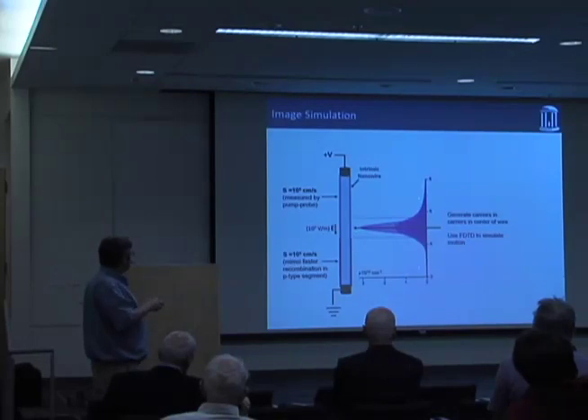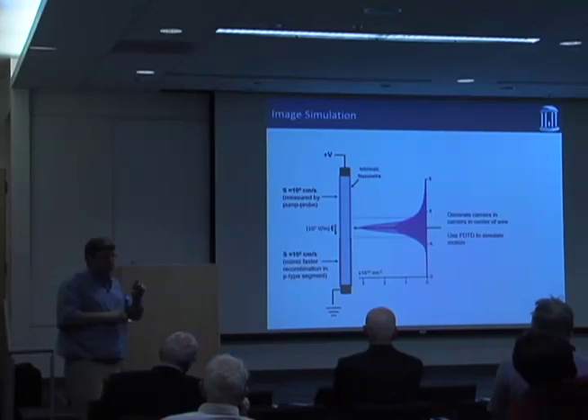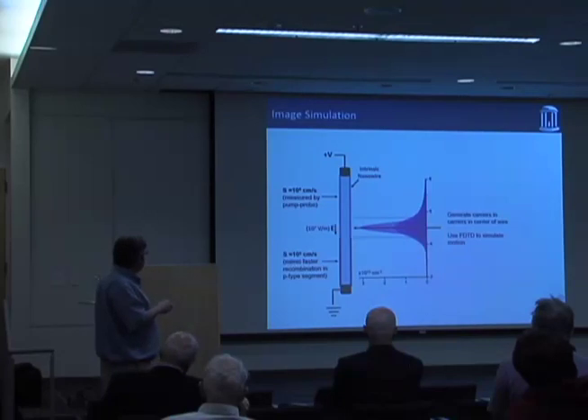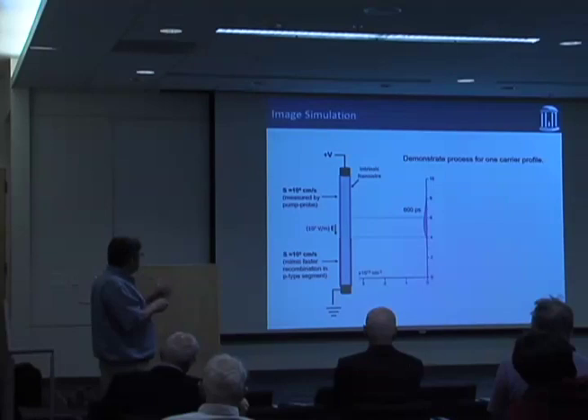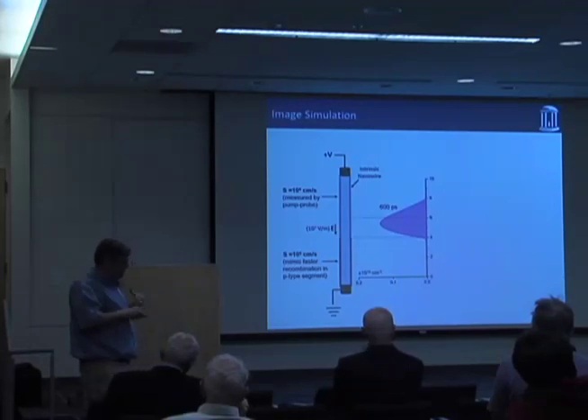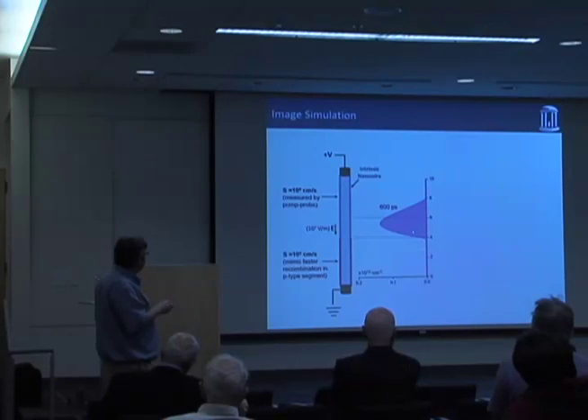and from the simulations we get the carrier densities for electrons and holes along the nanowire. When we excite it in the center, these dashed lines represent sort of the width or the size of the undoped region that we have in our junctions, to kind of give you some scale. We would then take each of these profiles, and say the 600 picosecond one, and we would use that to give us sort of the density along the nanowire. And you can actually see, it's hard to see in this image, but there is a little bit of charge separation that's going on in the wings here.